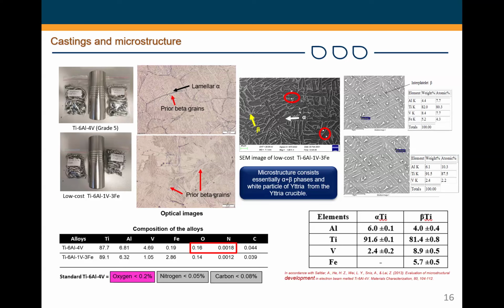Any of the intermetallic compounds were not in the experimental alloys, although we did find it in the Ti-6Al-1V-3Fe alloy, according to the XRD result that we have. But in terms of the partial substitution, what we had read in literature is that retaining a little bit of vanadium could suppress the formation of the TiFe intermetallic compound. We were able to establish that.